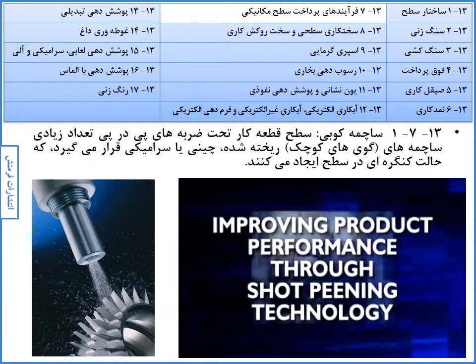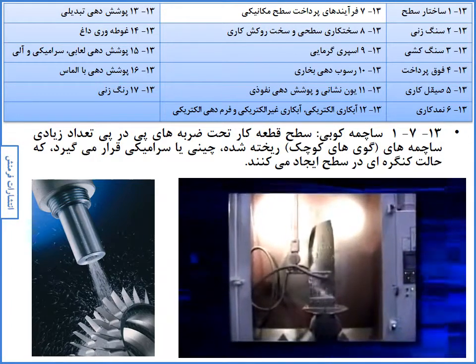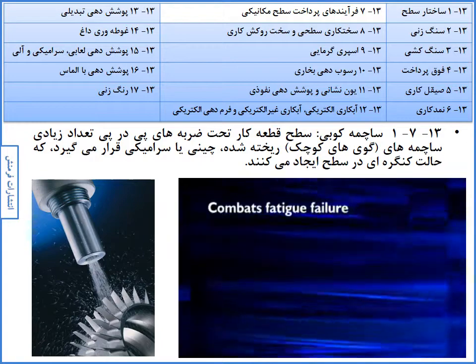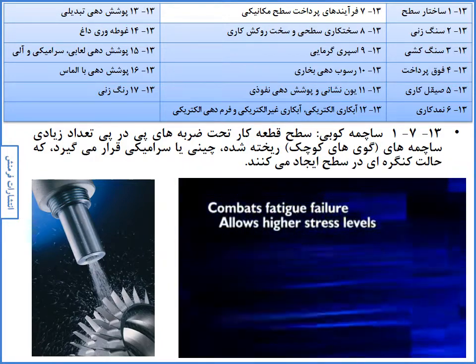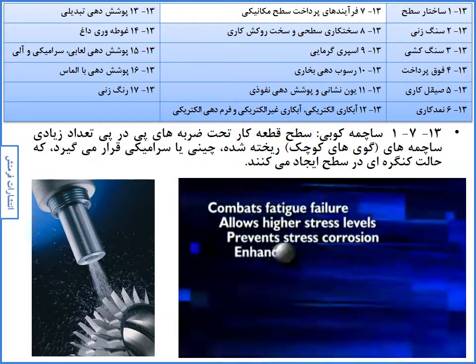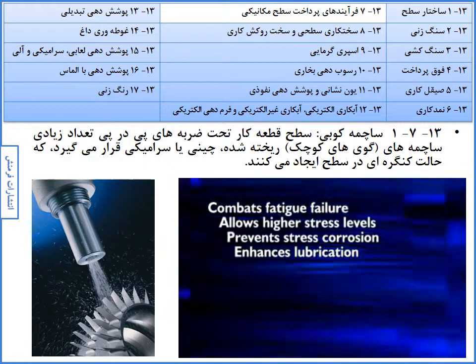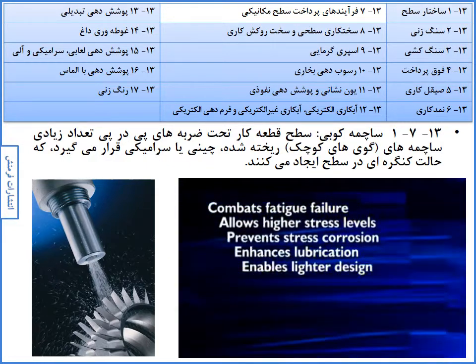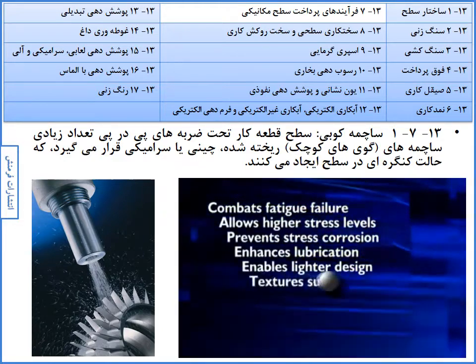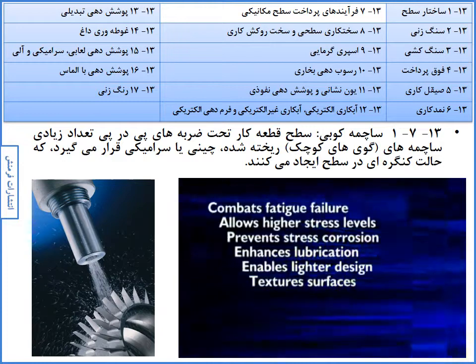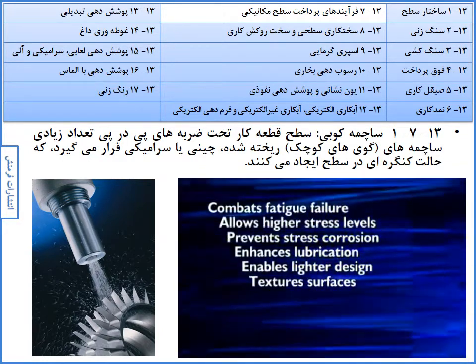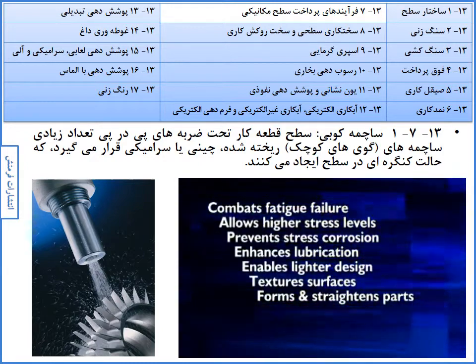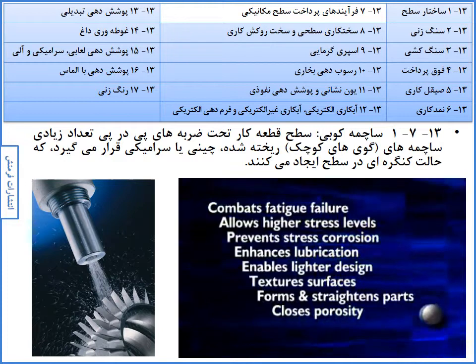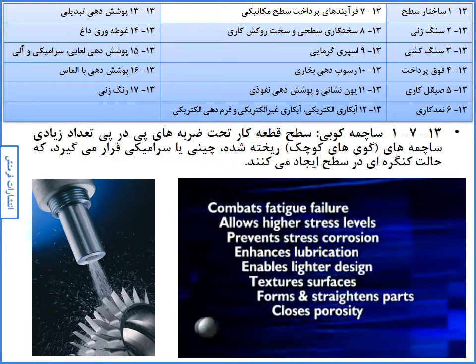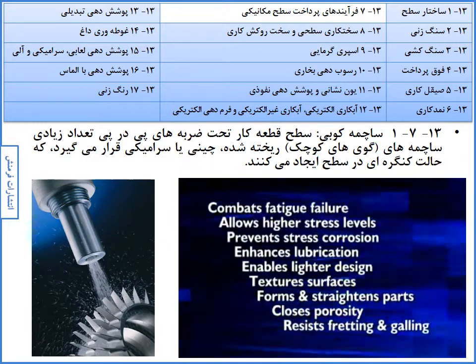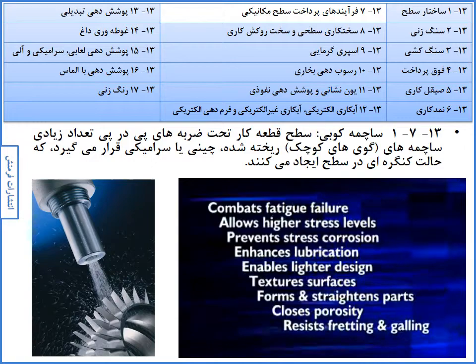through shot peening technology. Shot peening is the most economical and practical method of combating fatigue failure in metal parts. Shot peening allows parts to handle higher stress levels, prevents stress corrosion cracking, enhances lubricating efficiency on load-bearing surfaces, enables substitution of lighter metal without sacrificing strength and durability, creates uniformly textured surfaces that promote adhesion of special coatings or that meet cosmetic requirements, forms and straightens metal parts while inducing beneficial compressive stresses in surface layers, closes porosity in castings and powdered metal components, and resists fretting and galling by the combined action of work hardening and compressive residual stress creation in mating surfaces.